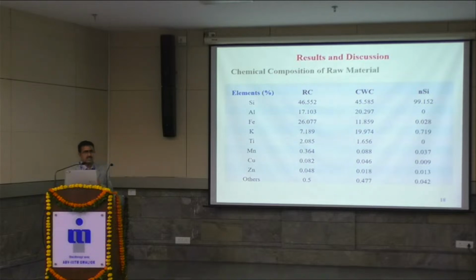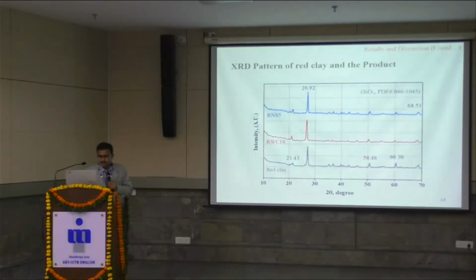This is the chemical composition, mainly silicon, aluminum, as well as iron involved in the process. The XRD pattern of the raw material, red clay, when added with the calcined white clay as well as nanosilica: this is the addition of 10% calcined white clay, and further, when 5% of nanosilica was added. Mainly in these, silica in the form of quartz was observed.